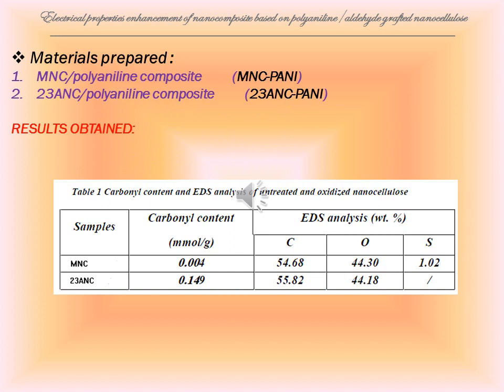To show the effect of functionalization of nanocellulose on the conductivity, it's important to measure the carbonyl content. In the case of MNC, the carbonyl content in millimole per gram equals 0.004, while in the case of 23 ANC, we have found that the carbonyl content equals 0.149.